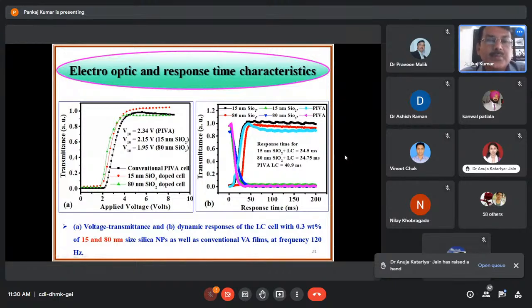But when we go to the 15 nanometer silica nanoparticles as well as the 80 nanometer silica nanoparticles, you can see the threshold voltage is reduced from 2.3 volt to 2.15 and 1.95 volt. Similarly, you can see in figure B the response times. For the PIVA cell, the response time is 40.9 millisecond. But in case of the silica nanoparticles, 15 nanometer and 80 nanometer, the response times are 34.5 or 34.75 millisecond.